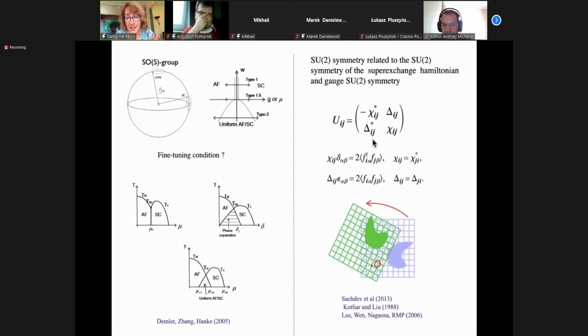Also, we know that at half filling, you have exact SU2 symmetries over there. And this was used even in a strong coupling version. Instead of having U1 gauge theories, you had SU2 gauge theories. So SU2 symmetry at half filling is basically the same as ours. So at half filling, you have an S wave and pi charge density wave. But for hole doping, this was generalized with the SU2 group by Patrick Lee and Xiao-Gang Wen in the old days. So it was an SU2 gauge theory. So you fractionalize electrons, but you keep the SU2 symmetry group.